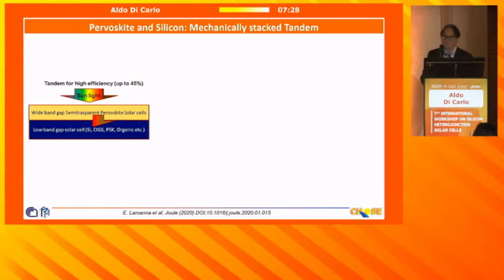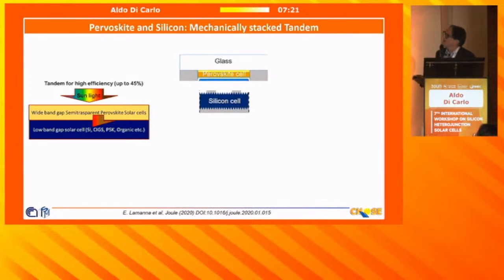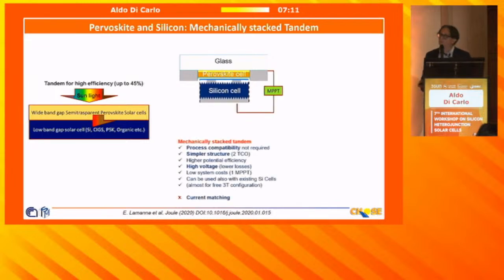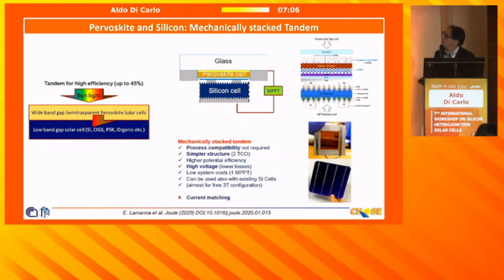Okay, so there is another way, as I was saying before, to do the tandem in a simple way, which is the following. We realize the perovskite solar cell independently from the silicon solar cell, and then we do wafer bonding between the top perovskite solar cell and the bottom silicon solar cell. So this is the top perovskite solar cell, and then we cut part of this conventional wafer of the silicon solar cell. So one can get good efficiency also in this way.